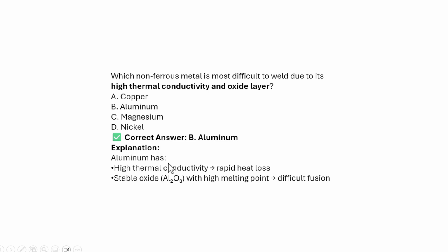Okay. So, which of the non-ferrous metals is most difficult to weld due to high thermal conductivity and an oxidation layer? Option A copper, option B aluminum, option C magnesium, option D nickel. The correct answer will be aluminum. Aluminum has high thermal conductivity that results in rapid heat loss, and a stable oxide Al2O3 with a high melting point that is difficult to fuse. So the generally preferred welding process is TIG welding with AC current, so that during the reverse polarity cycle the oxide layer cleaning takes place, which results in good welding.